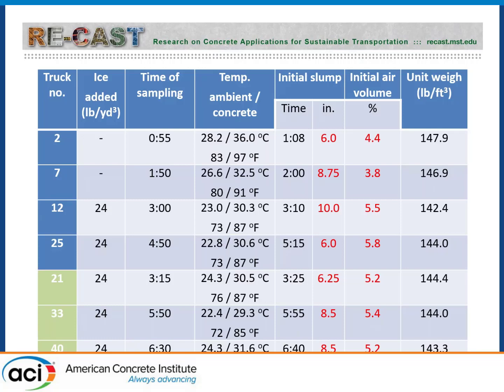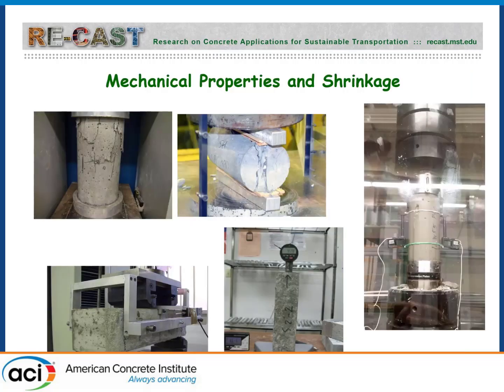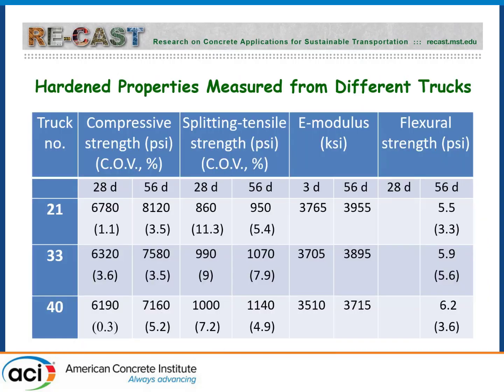You see the slumps, initial slumps, they varied between 6 and 10 inches. So they are not your 20-inch slump flow, but they're extremely flowable and very easy to pump. They were all air entrained. We took samples after 1 day, about 100 miles away, where the university is in Rolla, and subjected the concrete to a lot of testing. And these are some of the test results.